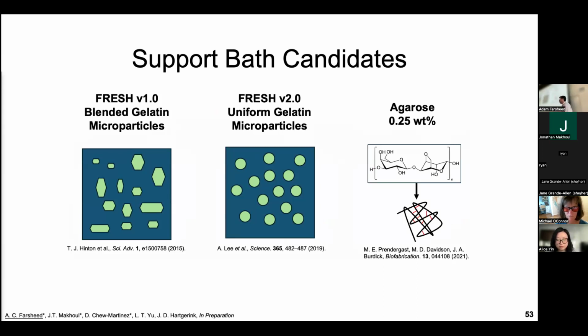And so there were 3 support bath candidates that we went about tackling this. And I just want to shout out that Jonathan in the back there, my undergrad, did a lot of the brunt work in terms of building these baths and testing them all out. But there were 3 candidates, the first being what we call fresh version 1, the second fresh version 2, and the third being Agarose. So fresh version 1 was a paper out of Carnegie Mellon, the same group that printed that full-sized human heart, where they took a gelatin block and used a commercial blender to blend up that gelatin into these microparticles, and then used that as your support bath as you're printing. The second is an upgrade on that, where instead of using a commercial blender, they're doing a fancier processing system to create these uniform particles that you can then use as your support bath.